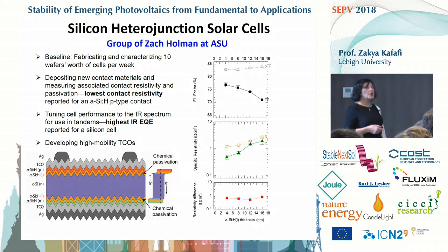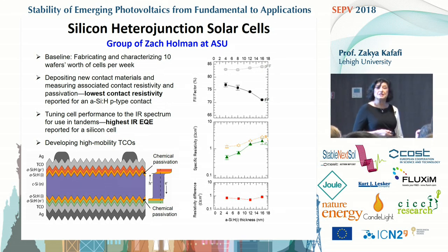I'm not going to talk too much about inorganic, because even though they have achieved the highest efficiencies, they are quite expensive and not practical for many applications. But it's worthwhile mentioning the work of the group of Zach Holman at Arizona State University, where he made some progress for the silicon heterojunction solar cell, developing new contact materials that have low resistivity, and was able to passivate them, so he was able to reach fairly low contact resistivities. He also was able to tune the cell performance for the IR spectrum in the tandem structures, and he achieved the highest IR external quantum efficiency reported for a silicon cell.